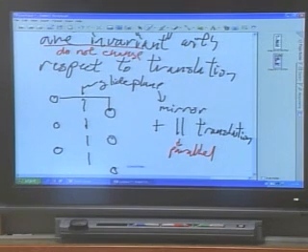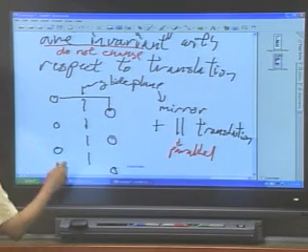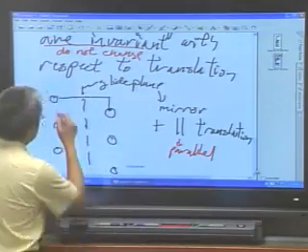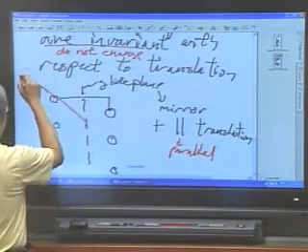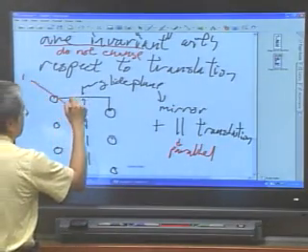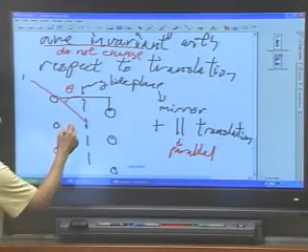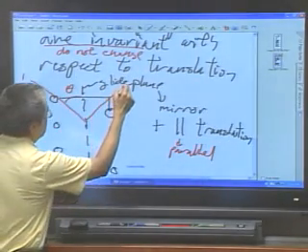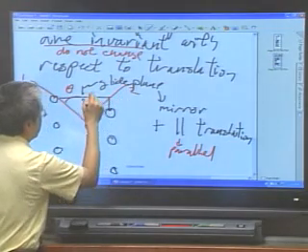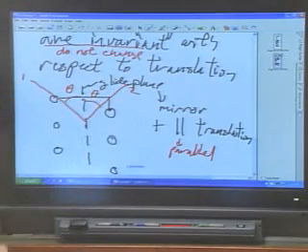Now, the question is, what sort of symmetry will the property have? Well, I will argue that the symmetry of the properties will be exactly the same as that of a mirror plane. That is, if I take a direction, let's say, again, which we'll call 1, and this direction makes an angle theta, then if I take this direction here, which is called 2, which makes the same angle theta, that 1 and 2 are equivalent. Now, why is that the case?